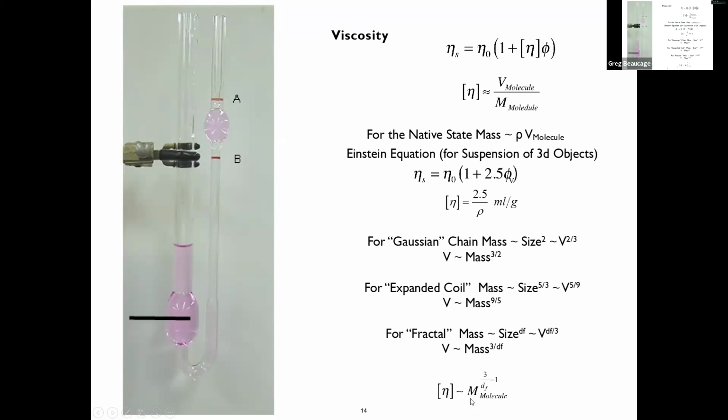So you can start looking at the molecular weight dependence. That's a Mark-Houwink alpha, a term, right? So it's K and a, the 2 Mark-Houwink coefficients. So these are tabulated in the Polymer Handbook, the K and the a. And you'll see that the a values vary between 2 and 0.5, basically. So kind of somewhere in that range. And then basically, if you know those 2 parameters, if you measure this number with this simple machine, you can get the molecular weight. Right, so that's called the viscosity average molecular weight.